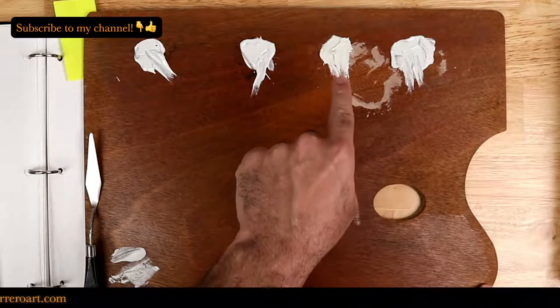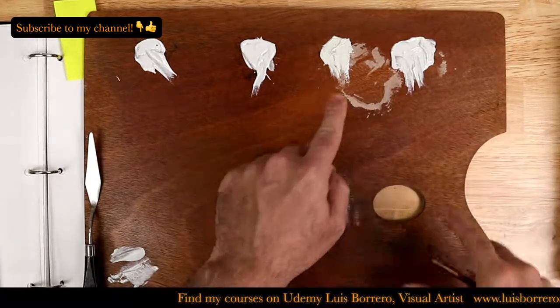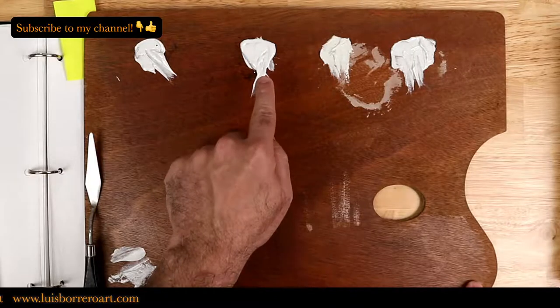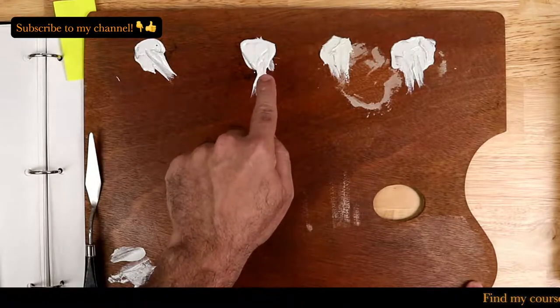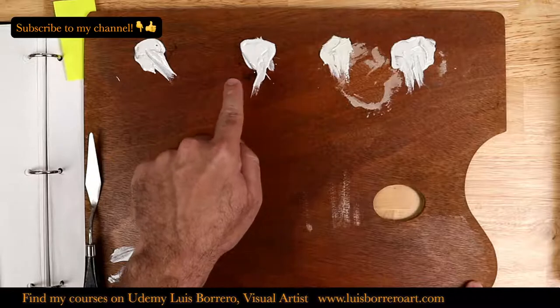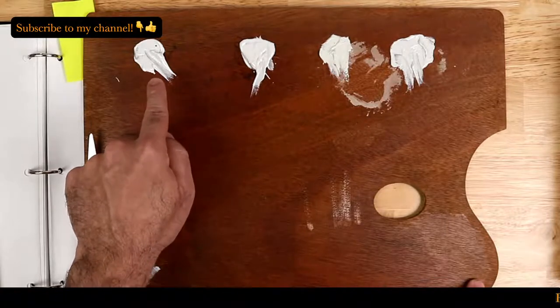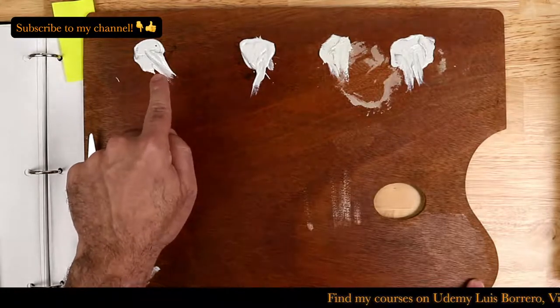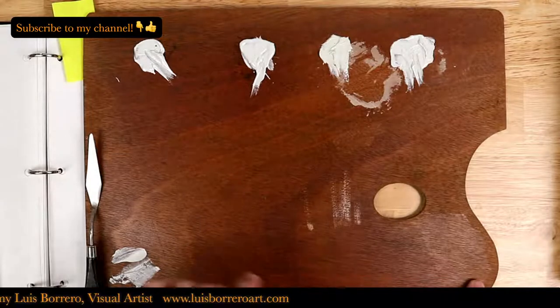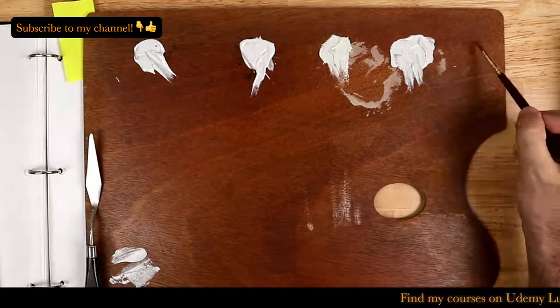In the second sample, I have linseed oil that has been cooked with litharge. The Italians call this type of oil olio cotto, or boiled oil. Then I have a third sample, which is stack process lead white ground for an hour with sun-thickened oil that has been purified as well. And then a final sample, which is purified, cold pressed walnut oil that has been boiled with litharge, red lead, and white lead, just as described by Palomino in one of his recipes. Let's go ahead and see how this will behave.